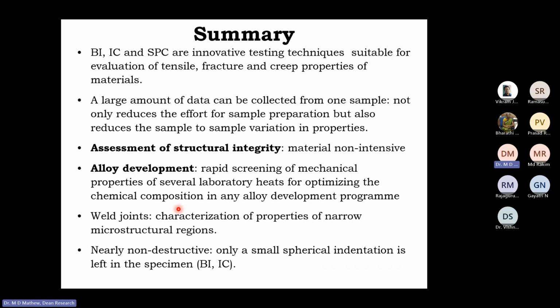So to summarize, ball indentation, indentation creep and small punch creep are innovative testing techniques that are suitable for evaluation of tensile, fracture, and creep properties of materials. A large amount of data can be collected from one sample, and that not only reduces the effort for sample preparation, but it also reduces the sample-to-sample variation in properties. So it's a very useful tool for assessment of structural integrity of materials, because you want to assess the properties without compromising the structural integrity of a component or an equipment. So it has to be material non-intensive. You cannot remove large parts of the component to do the evaluation. So from that point of view, it's considered to be material non-intensive and suitable for assessment of structural integrity.